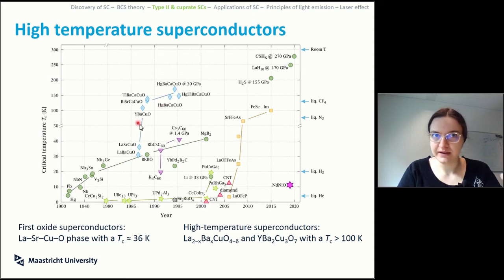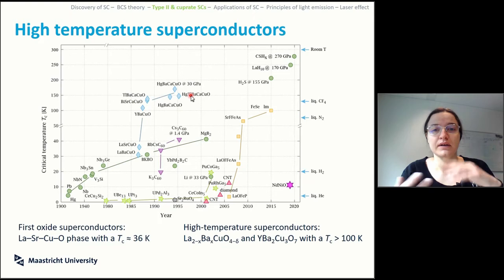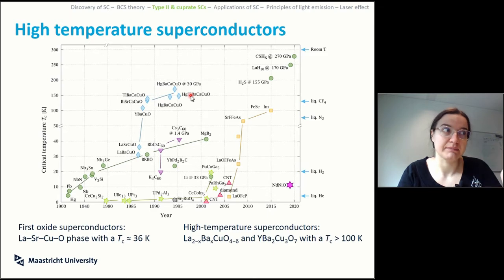So this was the moment when a lot of solid state people started to realize that modifying the material could achieve something that could go from a general super low temperature behavior to a behavior that you could actually push to higher temperature. That said, you can notice that there has been a bit of a lag in the field. There has been nothing so far that actually reaches the very elusive point of room temperature superconductivity, which will be the dream. But so far, nothing has really cut that edge. It's very difficult to reach, and the field has been trying and failing and trying and failing to make something that actually breaks that limit.